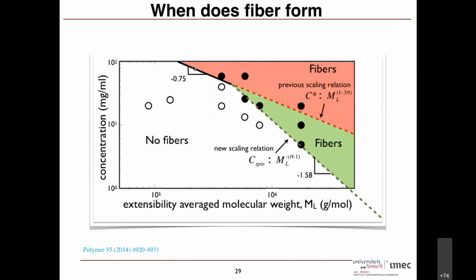And this is what we figured out. The previous scaling law said that if you are above this red line, you get fibers, and below the red line, you don't. But now we found that there is actually a region where, if you have these high molecular weight polymers, you will get fibers in this green region also. This is very useful for my transparent conducting electrodes, where I want to make them mostly from metals and a very small amount of polymer. So my trick was to use a very small amount of high molecular weight polymer, add gold nanoparticles, and you can make fibers.